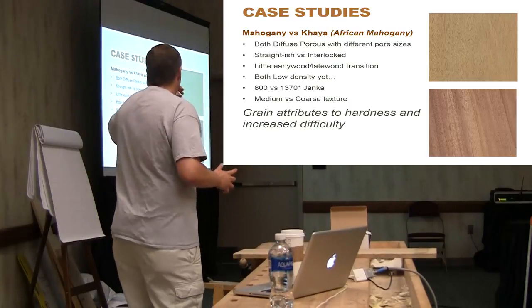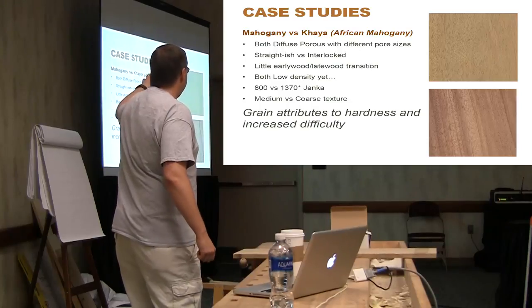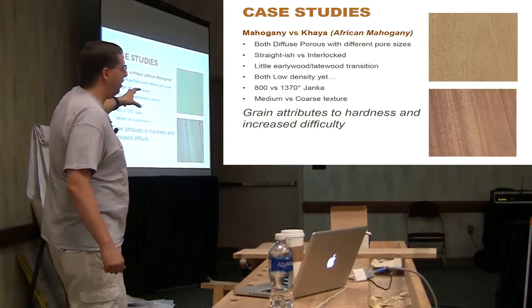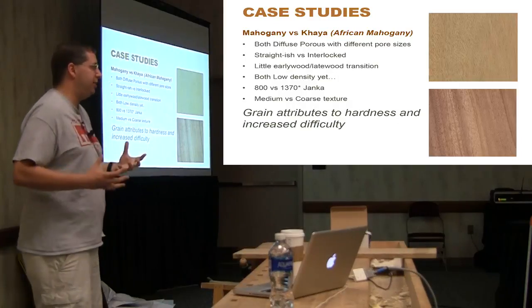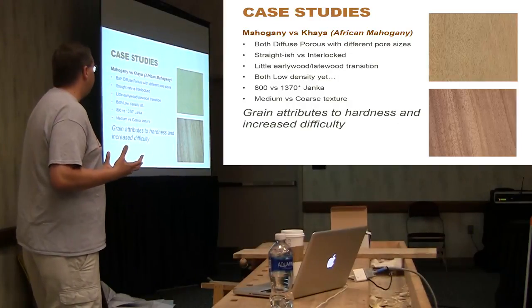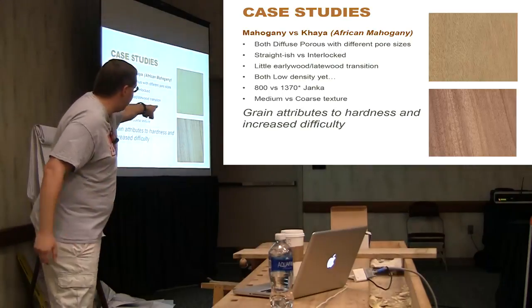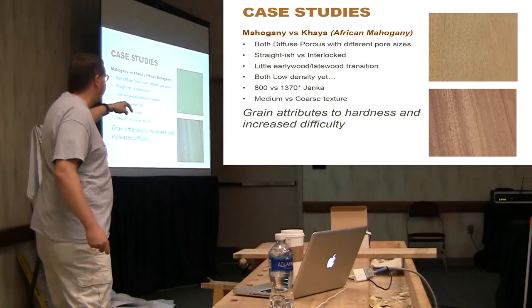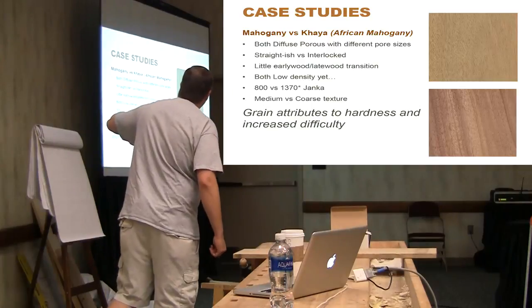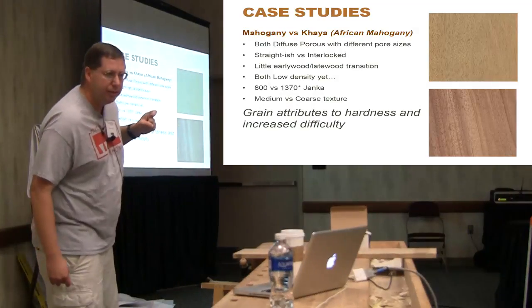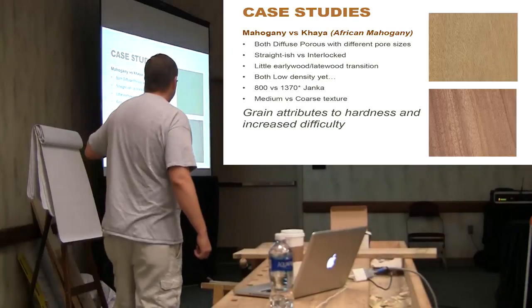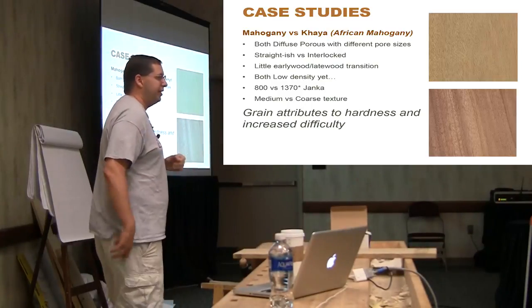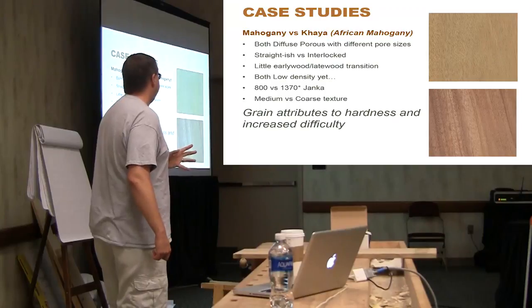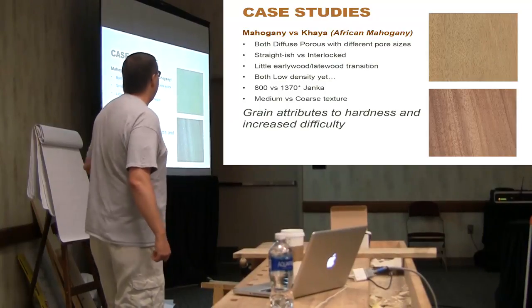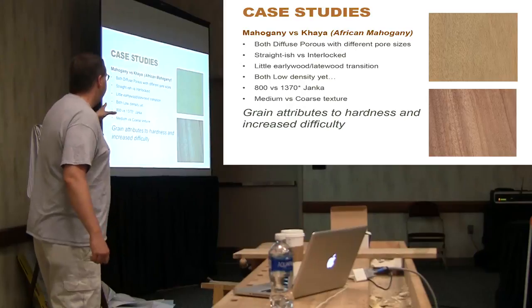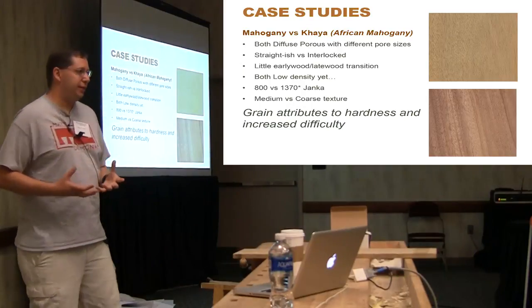So we have very little early to late wood transition in genuine mahogany, but in African mahogany, although it's not a big transition, your interlocked grain and your larger pore size will create that striated appearance you see. Khaya's on the bottom, genuine's on top, and that top picture is really green. It doesn't look that way on my screen. So they both have a relatively low density, like 0.44 and 0.45, I think. But you can see a dramatic hardness difference, and the grain is what creates that hardness differential.